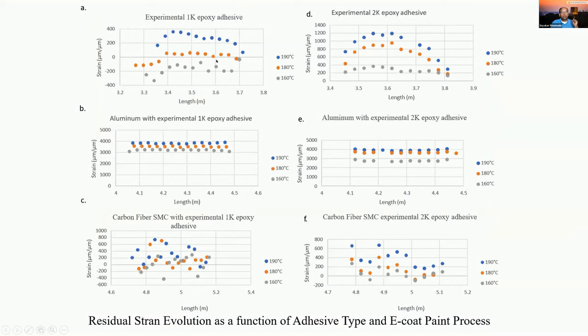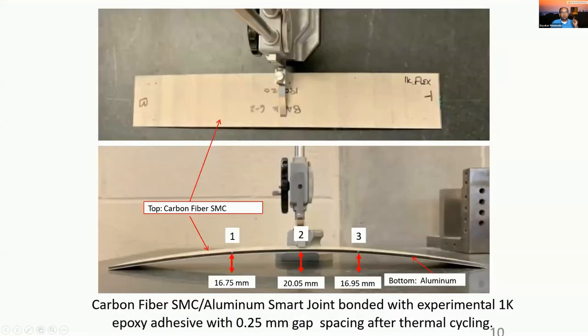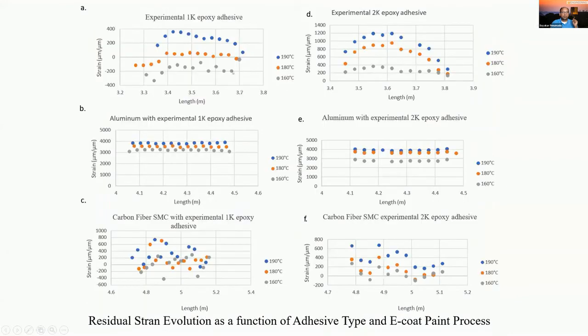So what we can actually do is now we embed a smart joint with this fiber optic and actually monitor what happens to this material system, this joint, as it goes through, for example, a paint process, E-coat process in this case. And as it goes through the initial temperature ramp and the subsequent temperature ramps, and as it goes through cooling and reheating, eventually at the end of all of that cycling, we can actually continuously monitor as a function of location how much is the residual strain. And then by using suitable rheological performance of the adhesives, we can minimize the locked-in residual stresses.